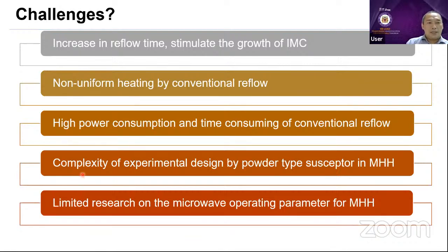And then some complexity of experimental design by powders, such as if you can see that my previous slide that they are using the silicon carbide powder, iron powder, but in this case we are using the wafer. Wafer is the plate, easy to use compared to the powder. We don't want that this powder will contaminate our sample and so on. If you use the silicon wafer, it's just nice at the bottom of the sample, so there will be no direct contact to them. And then for sure, there are limited research on the microwave operation for the joining, so this open a very good opportunity for us to do the detailed research on this.